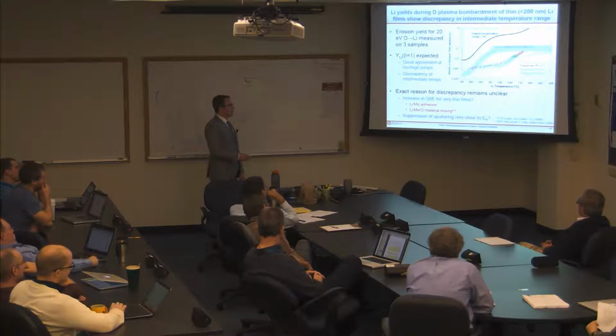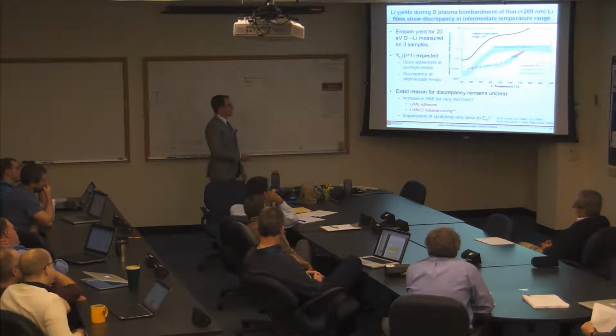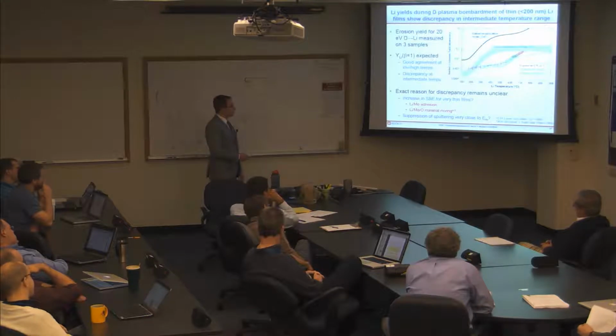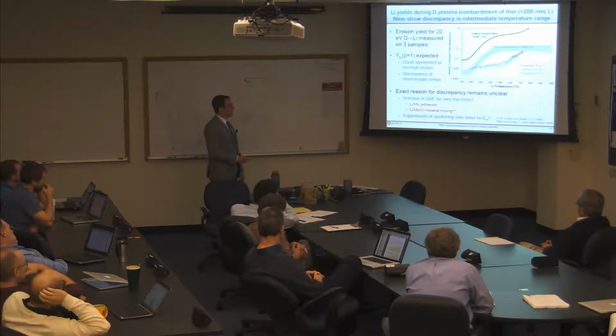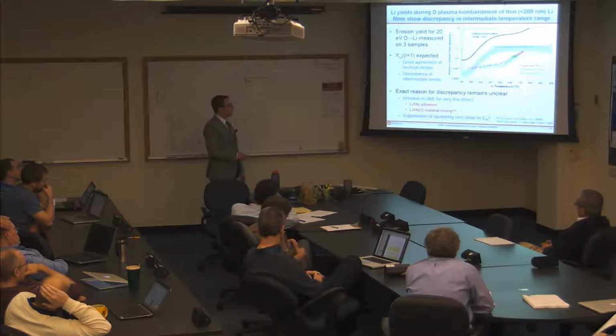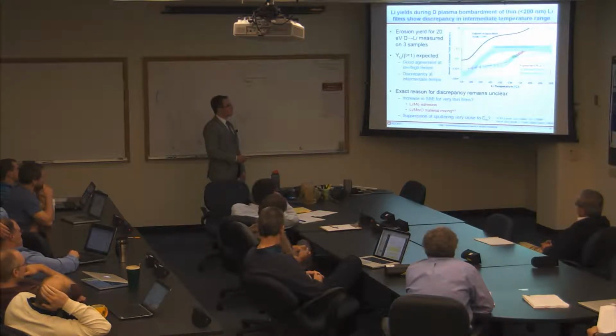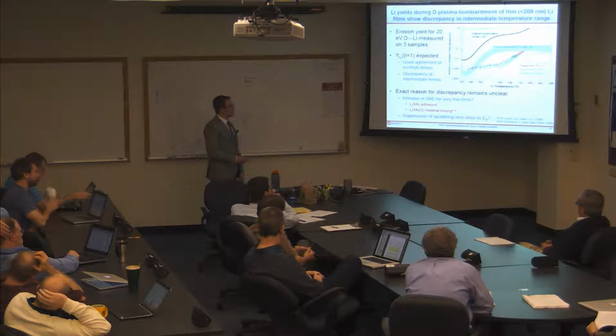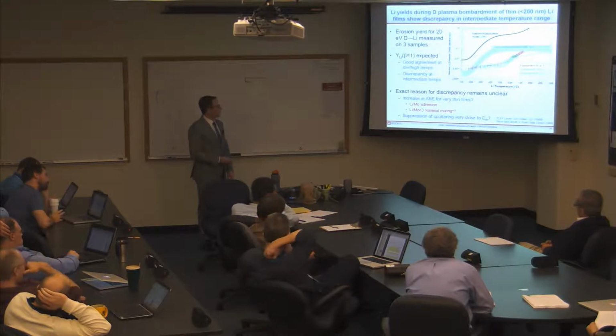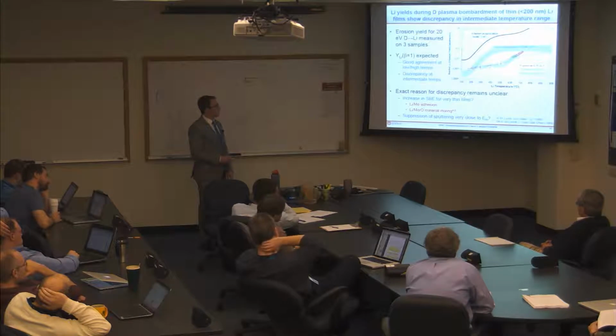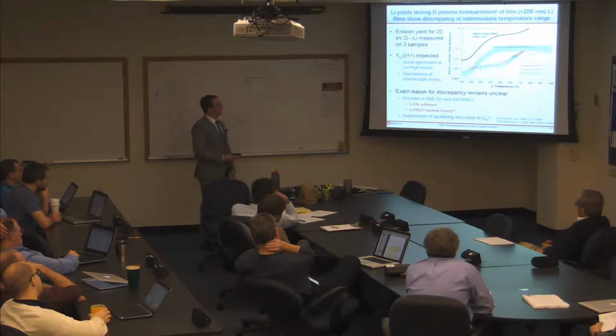And again, the error band is the difference between whether or not you assume you have another deuterium monolayer on your surface. And so you actually seem to get pretty good agreement at very low temperatures, at sort of room temperature. Again, the SDTrim yields seem to underpredict by about a factor of maybe 3 or so. And then at very high temperatures, up at 600, 700 C, you seem to be approaching what the atom evaporation model predicts. But in between those two, from about 300 to 600, you actually do have a discrepancy here. And the different colors are 3 different lithium samples. So we did this experiment 3 different times, and we got consistency between the measurements, but not agreement with the model here.